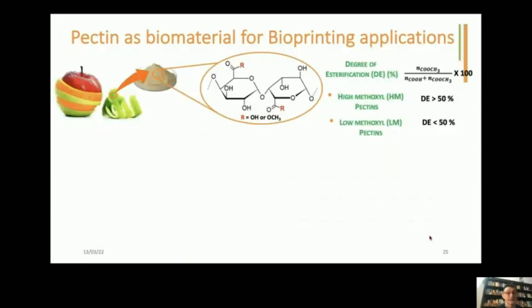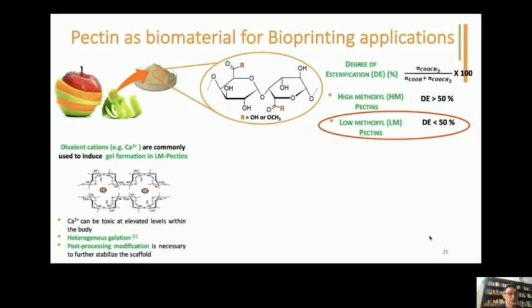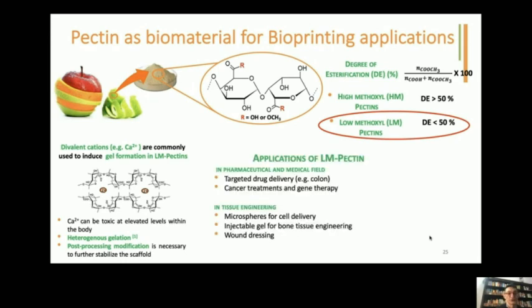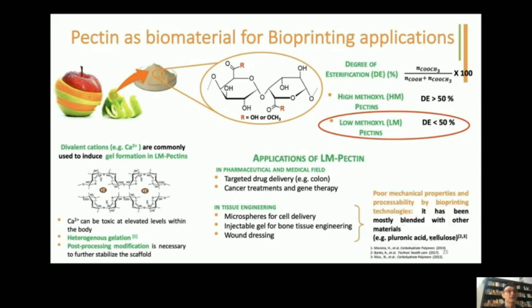The particularity of this pectin is that it is a low methoxyl pectin that can be used for gelification because divalent cations such as calcium ions can be added in order to induce the gelification. So now pectin is used as a targeted drug delivery system for colon pathology or for cancer treatment and gene therapy. It is also used in tissue engineering as microspheres for cell delivery or injectable gel for bone tissue engineering and wound dressing. But the problem with this material is that it presents poor mechanical properties that are not good for bioprinting technology. Normally they try to add other materials to pectin, like pluronic acid or cellulose, to improve it.